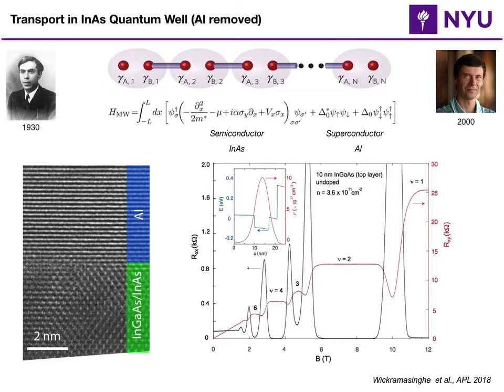So we have characterized these materials. Obviously, you want a very good superconductor and a very good semiconductor. And the key is the interface, right? Because to realize that Hamiltonian, all of those terms will really come together at the interface. So we have done individual characterization. For example, you can remove the aluminum selectively on top of the quantum well and look at the quantum Hall physics. For example, I'm showing you here Rxx as a function of magnetic field, and you see the oscillations and quantum Hall states in this material. Because the quantum well is near the surface, the mobility is limited to 20-30,000 centimeters squared per volt second.